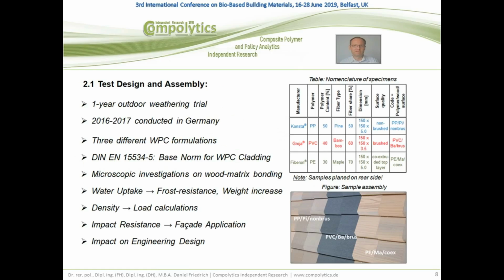So we wondered about the long-term structural and physical performance of such cladding profiles in practice, and we conducted a one-year outdoor weathering trial where we tested 3 different compounds supplied by 3 manufacturers. Konsta is a manufacturer providing polypropylene-based profiles with pine fibers. Goya is another manufacturer and supplier in Germany with a PVC based WPC with 40% content of polymer where bamboo fibers are embedded, and Fibron is a supplier where polyethylene is used with 30% content and maple fibers up to 70%.